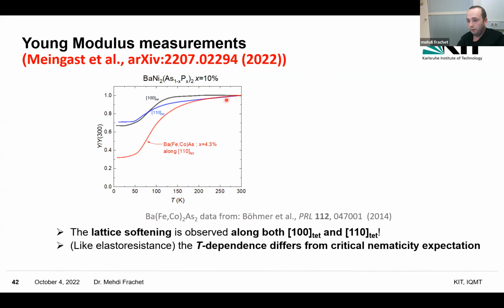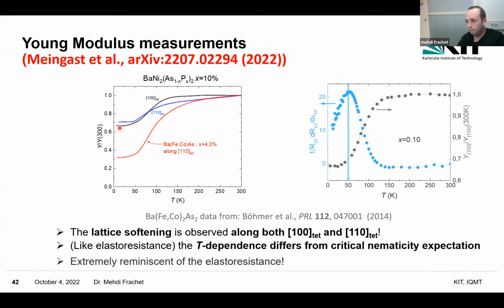You can also compare this with the cobalt doped barium iron arsenide, and you see that the temperature dependence is quite different between this critical nematic barium iron arsenide doped with cobalt and, in particular, this 100 Young modulus in the nickel compound. Okay. But one thing which I find very interesting is to compare this Young modulus data along 100 again with the elastoresistance, and you see that both have kind of the same temperature dependence. The lattice softening that you see is associated with a rise of the elastoresistance, and the saturation of the lattice softening is associated with the decrease of the elastoresistance. So that's something we are still investigating.